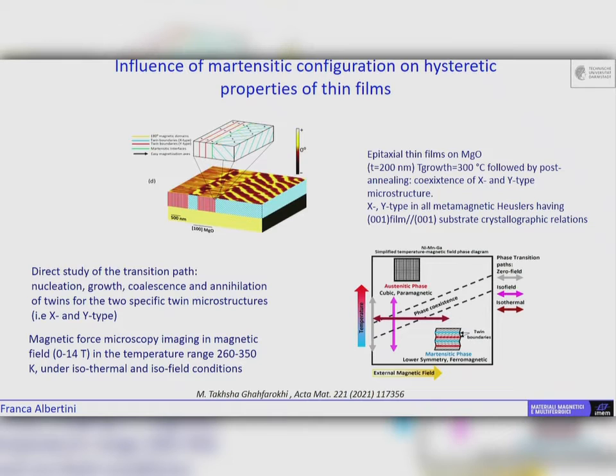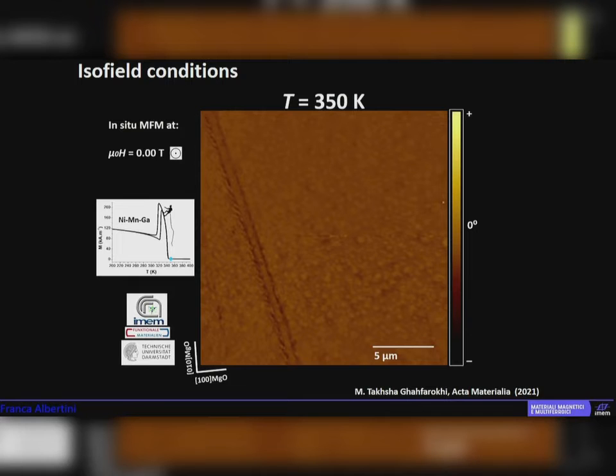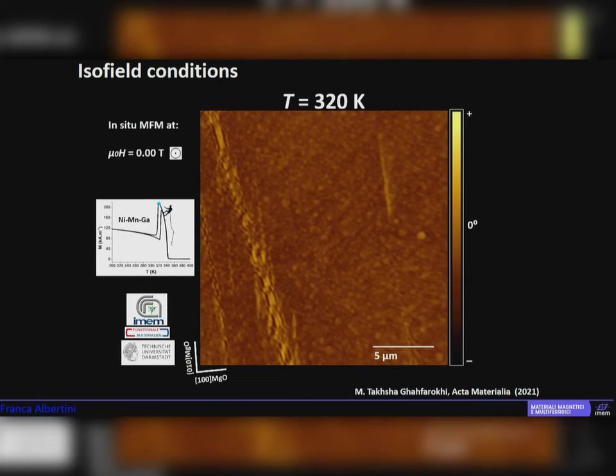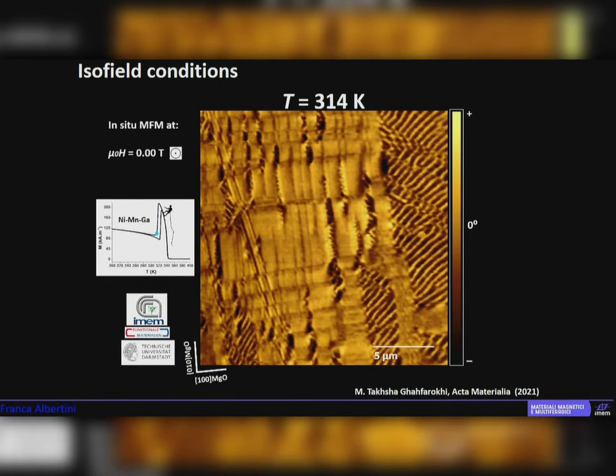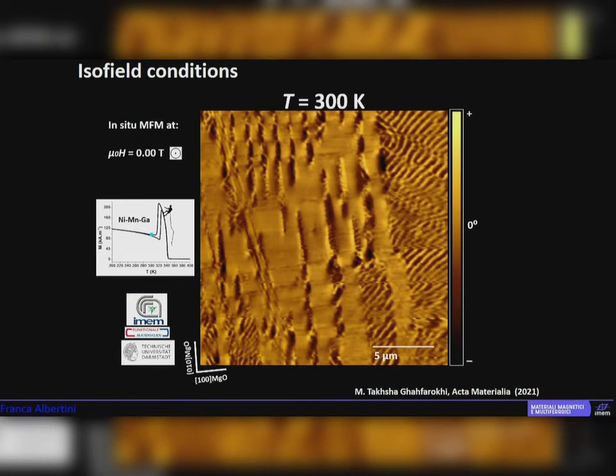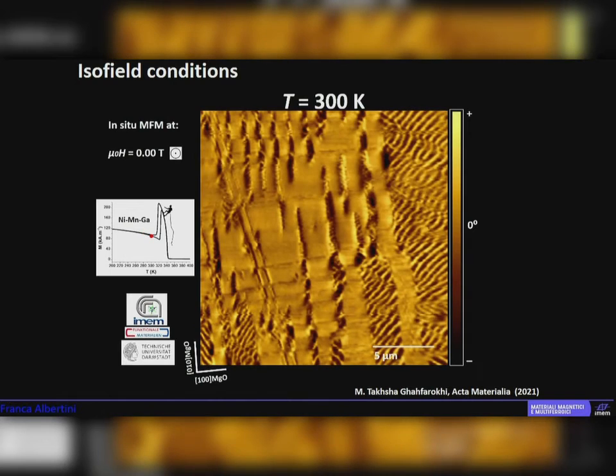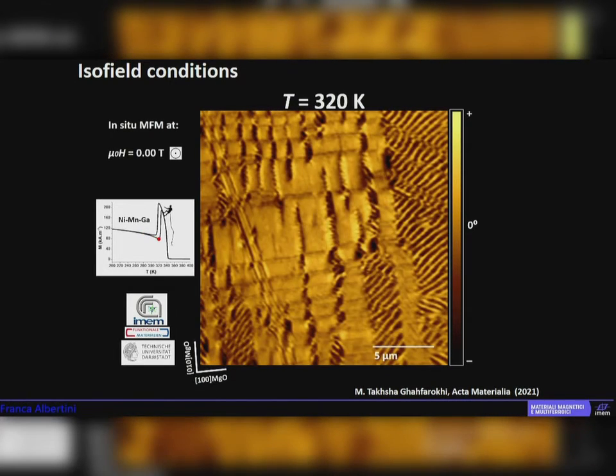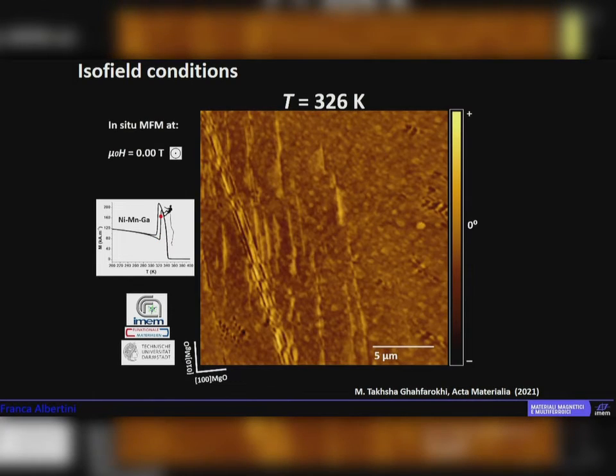And we have made a magnetic force microscopy imaging experiment in a magnetic field up to 14 Tesla and in a temperature range close to the transition temperatures, following these paths in iso-field measurements by changing temperature and by applying a field at a certain temperature and inducing the crossing and inducing the transformation. Okay, you can see that by decreasing temperature we obtain the Martensitic transformation, and appear the Martensitic features of these materials. First, the Y-type Martensite, and then the X-type that is along the 45 degrees direction.